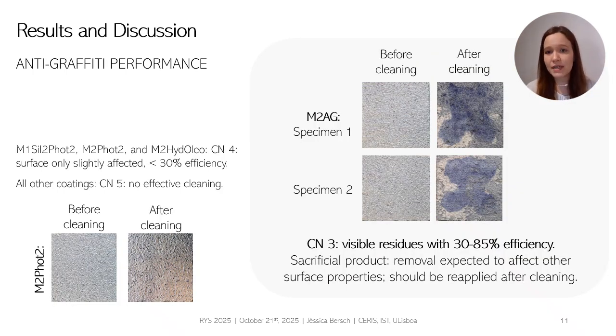For anti-graffiti assessment, none of the studied systems reached the best performance possible, which would be 100% removal of the spray paint. The best performing configuration was mortar 2 applied with the sacrificial anti-graffiti product. Here I show pictures of the 2 specimens tested before and after cleaning with the low pressure water steam jet. These specimens were classified with a class CN3 that represents visible residues with 30 to 85% efficiency. Since the anti-graffiti is a sacrificial product, its removal is expected to affect other surface properties such as gloss, and it should be reapplied after cleaning.